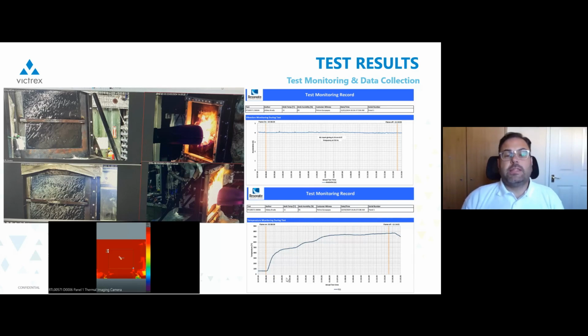The thermal camera, as opposed to the thermocouple that I talked about in the previous slide, which is a spot measurement, the IR camera, the thermal camera, is an area measurement. And the graphs that you see on the right, the top one is the vibration, making sure that the vibration is at 50 hertz or 4 Gs, in our case, depending on the mass of the panel. So it had to be around 4 or 4 point something Gs.